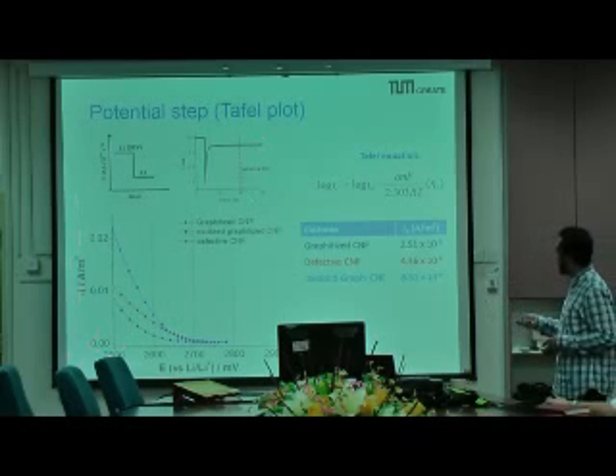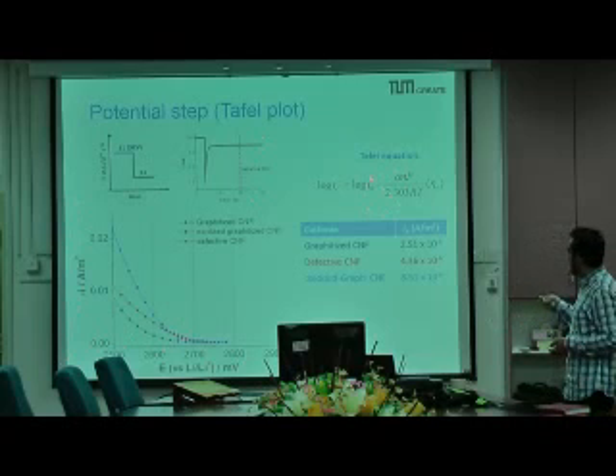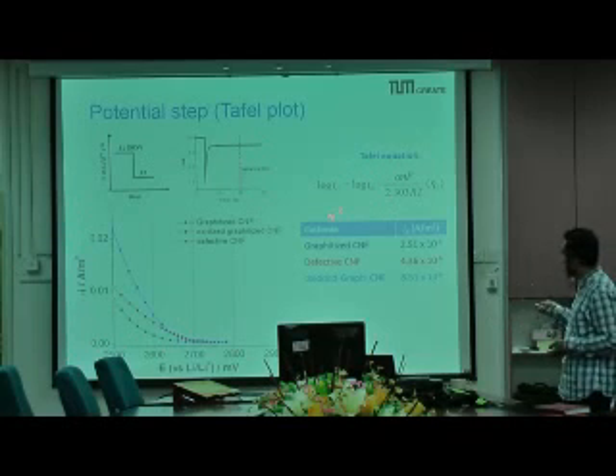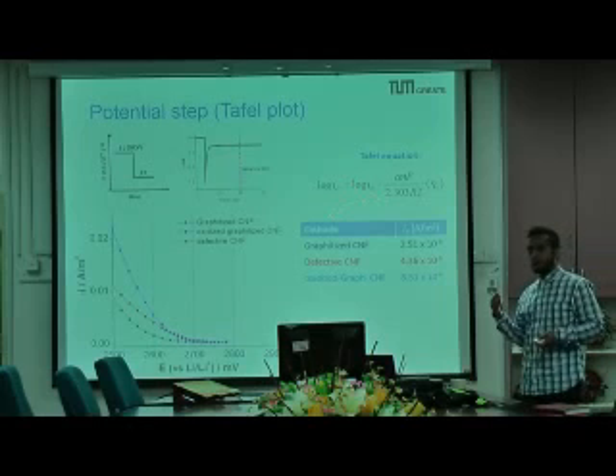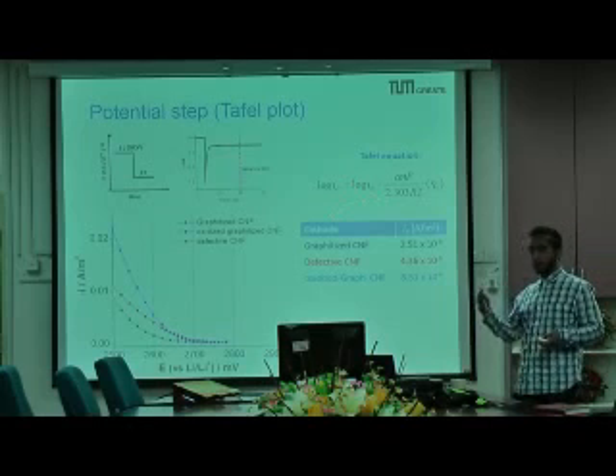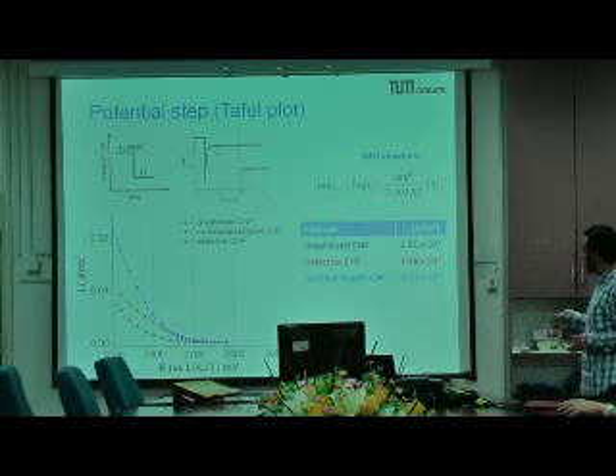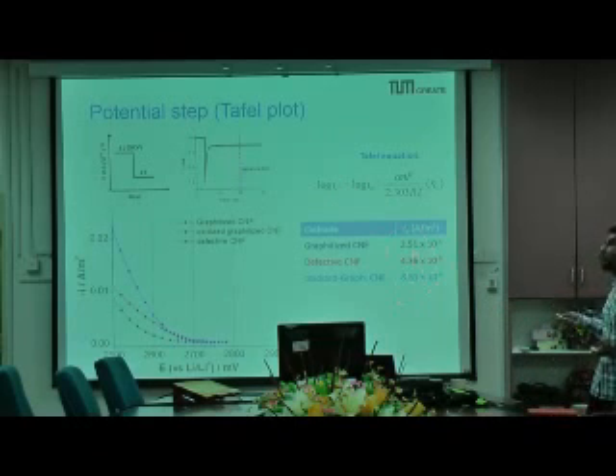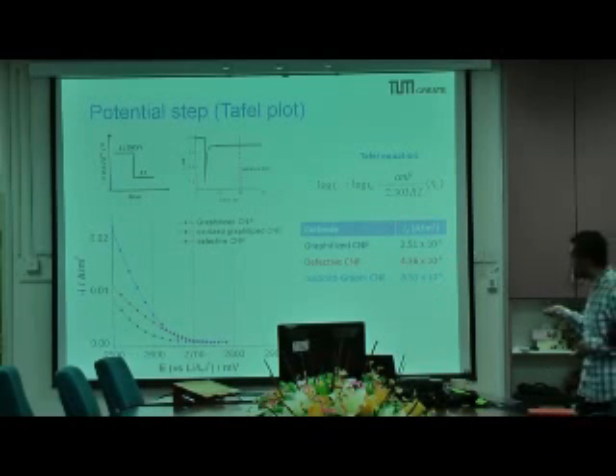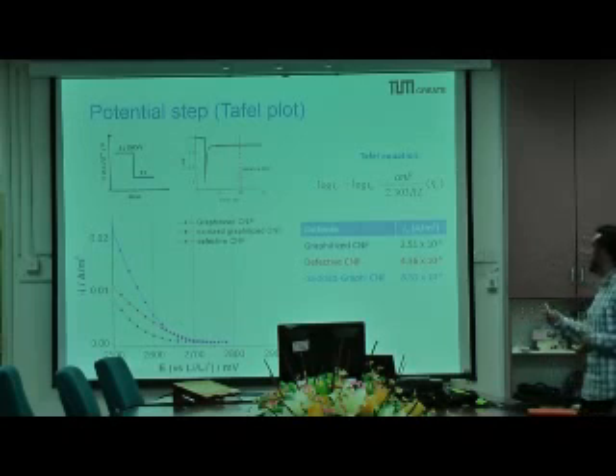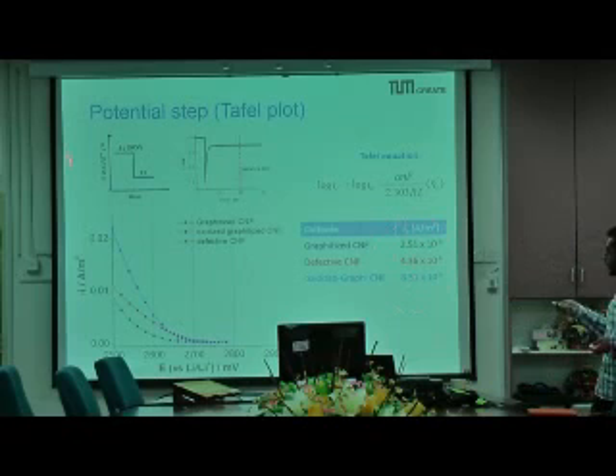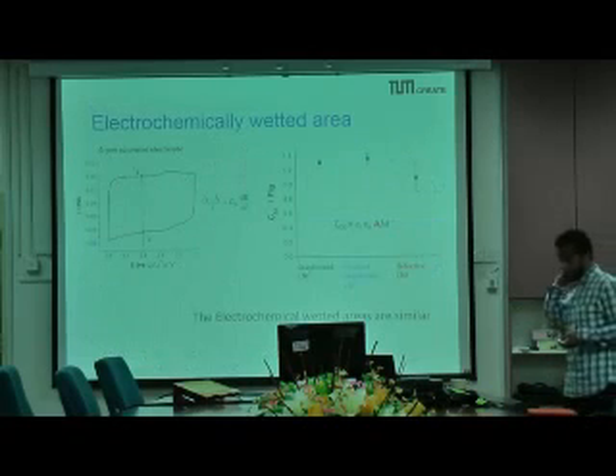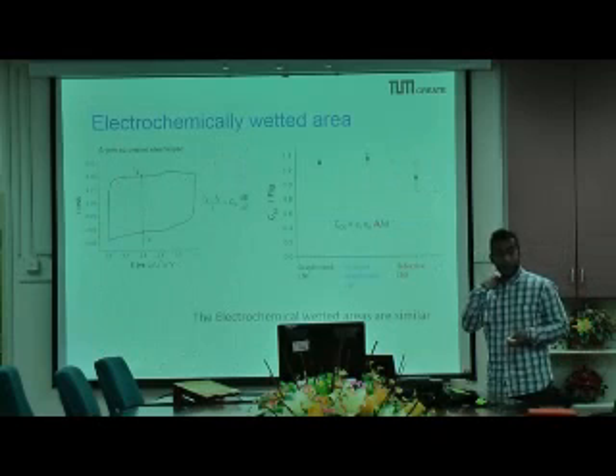And if you plot the current versus the overpotential and you get the intercept, that is the exchange current density, the I0, that is the activity that the material has at open circuit voltage. So this means the amount of oxygen being reduced at equilibrium potential. Of course, the higher this value, the more active the material is. So the trend is quite clear: when you introduce defects in the graphitic material, you increase the activity for oxygen reduction. Of course, one can say that if you oxidize the material, then you increase the surface area.